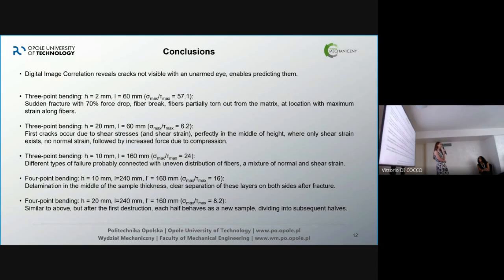So it's really important to analyze the microstructure, and it's also what's happening, and here the digital image correlation really helps us because we could predict this information using it. Without the digital image correlation, we would have nothing because the force would be still okay, but this local strain would lead us to really catastrophic results.